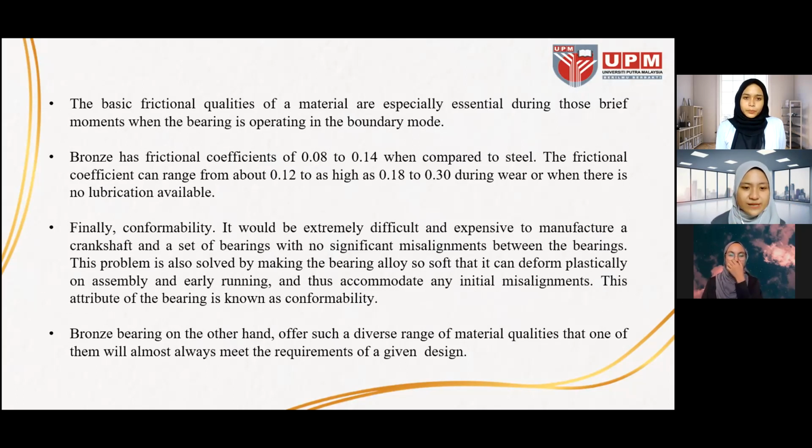crankshaft and a set of bearings with no significant misalignment between the bearings. This problem is solved by making the bearing alloy so soft that it can deform plastically on assembly and early running, and thus accommodate any initial misalignment. This attribute of the bearing is known as conformability. Bronze bearing, on the other hand, offers such a diverse range of material qualities that one of them will almost always meet the requirements of given designs. So next,